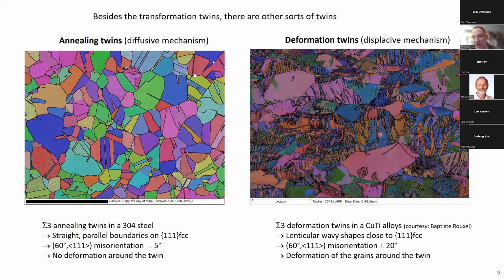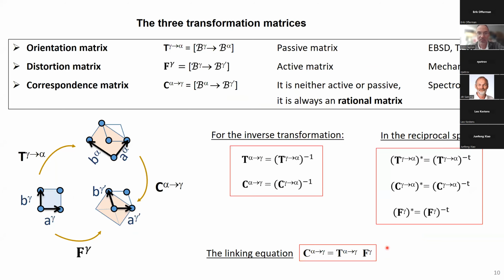There are no new phases. All that you see is FCC. Here it's a copper titanium alloy. If you need to find them, you can enter in your EBSD map the special misorientation of 60 degrees, but you have to add more tolerance angle to define them.